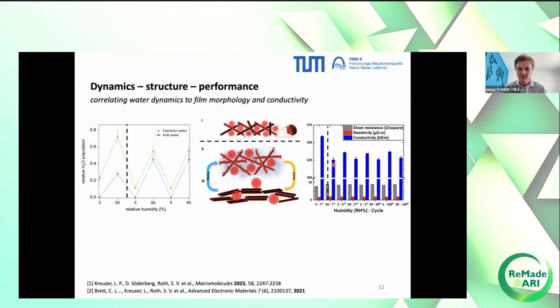Once we dry the system, PEDOT:PSS rewets on the cellulose fibrils, and the conductivity increases again, but it never reaches this initially highest state. So we never go back to this initially dry morphology or this ratio of hydration water, but we go to something else, which corresponds to, let's say, an intermediate conductivity. So it's a very nice correlation, not only between dynamics and structure, but also to a macroscopic functionality.